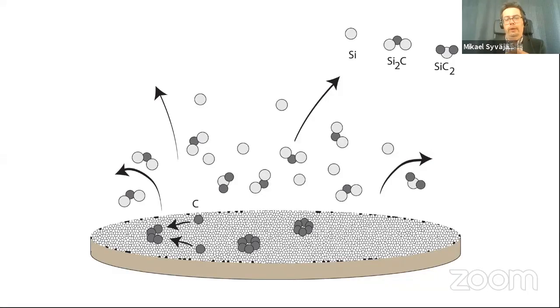And let me mention another avenue from the silicon carbide point of view. In the growth, we have silicon and carbon. So we're trying to combine them to grow the silicon carbide. So that is for the growth. And when we initiate this growth, we get vapor species and they leave the surfaces and continue to do some things. And actually in one way, when we heat up silicon carbide, a little more silicon leaves the surface than carbon. So if we are making a wrong growth process, there is graphitization of the surface, which is very